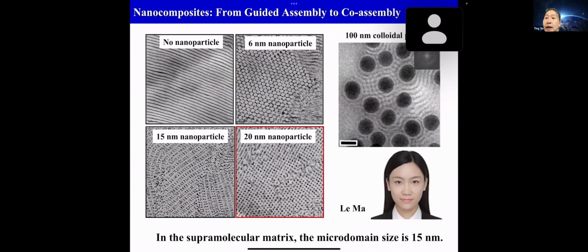So with that, we actually can really begin to pursue forward, because if the system is miscible, you no longer have this templated assembly of nanoparticle. You can begin to think about co-assembly, because in essence, you're dealing with multi-component blends, and you can basically back calculate what the entropic contribution from each system is. And indeed, based on the data, what you show here is that we can start to expand the particle size without disrupting assembly, and the co-assembly indeed leads to new morphologies we haven't seen before.